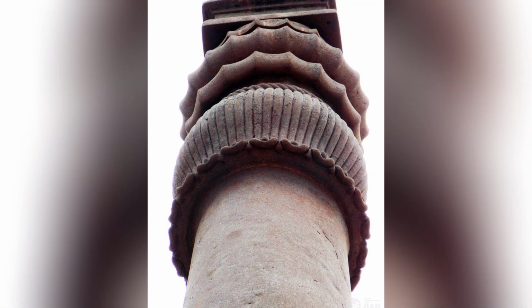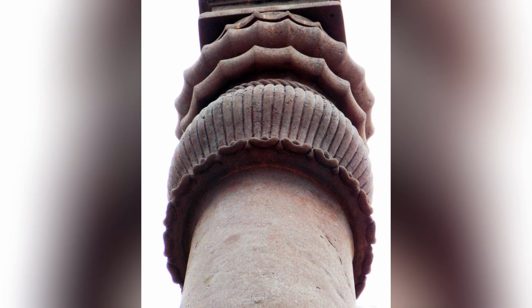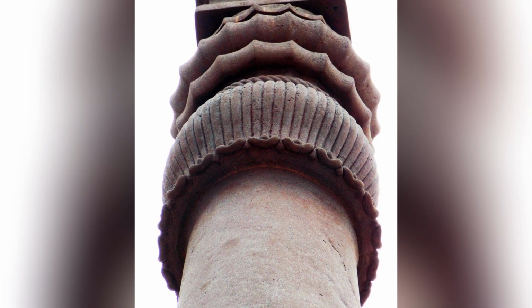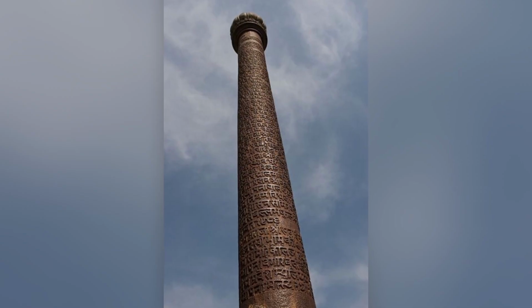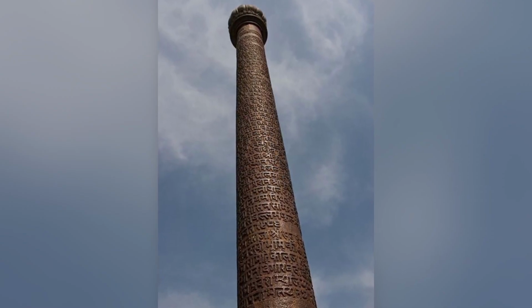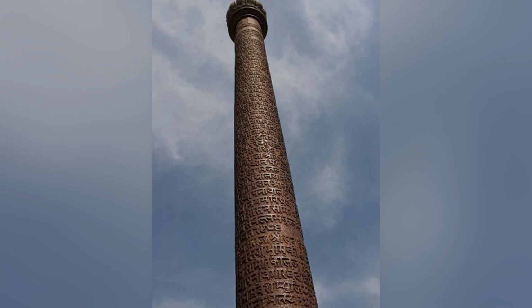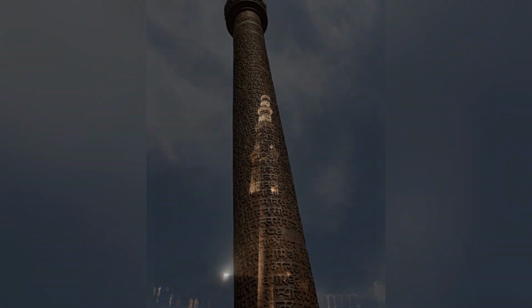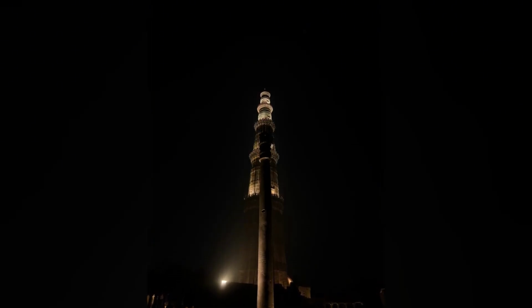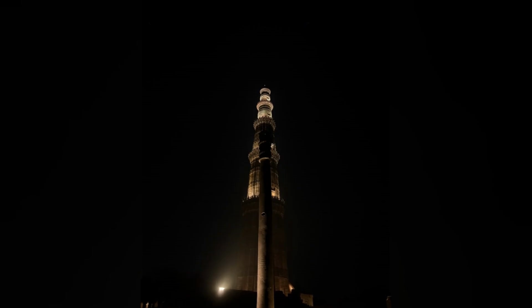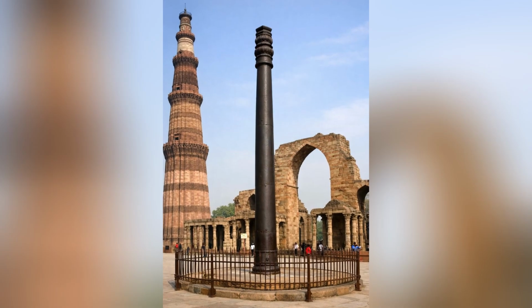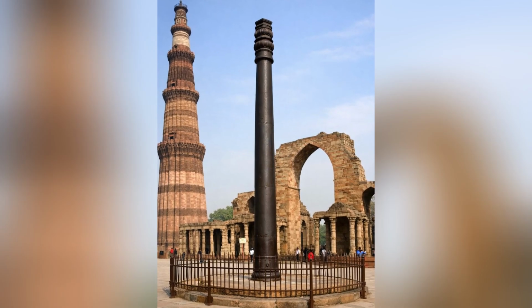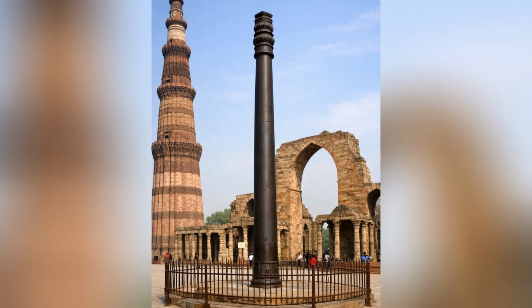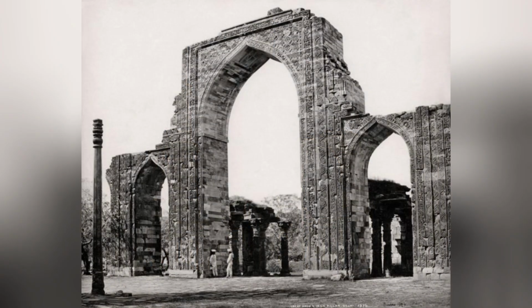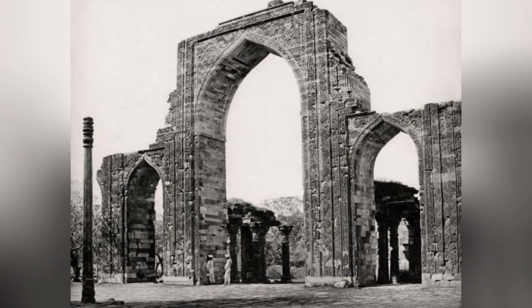The Konark beams, which were used as structural supports in the construction of the temple, are made of an iron that is similar in composition to the Delhi pillar's iron, with a high phosphorus content and a low carbon content. The beams exhibit similar corrosion resistance to the pillar, with a protective film of iron phosphate compounds on their surfaces that has preserved them from significant corrosion over a period of approximately 8 centuries. The similarity between the Delhi pillar and the Konark beams confirms that the corrosion resistance is a systematic property of Indian bloomery iron produced from phosphorus-rich ores, rather than a unique property of the Delhi pillar alone.